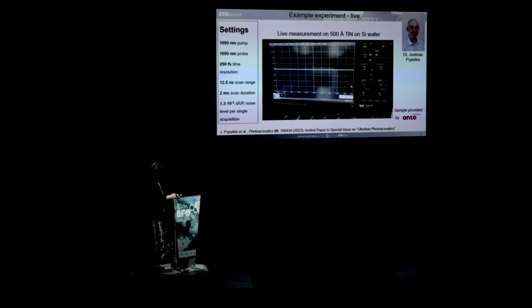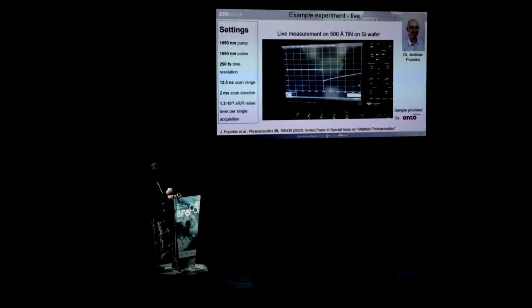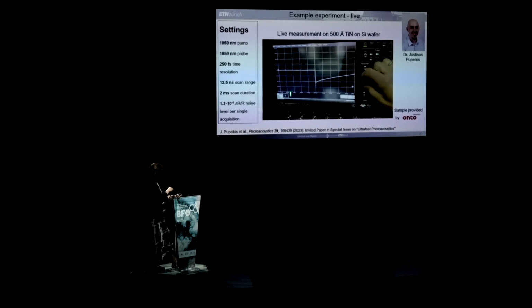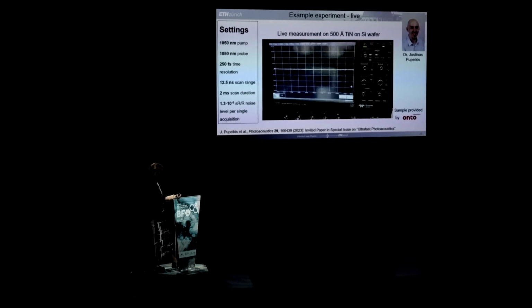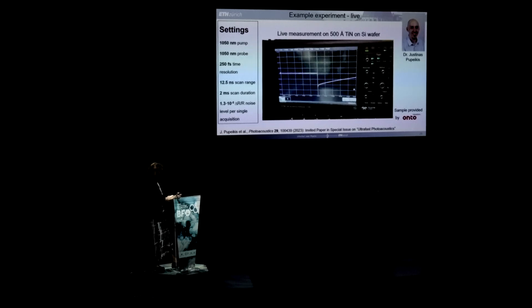So this is, for example, a test where we got a test sample with a commercial provider, which are doing this type of measurement, but still with mechanical delay lines. And so we did this measurement on a thin layer on silicon wafer, and you can see, boom, there are the fluctuations. You right away get the thickness out of these materials.